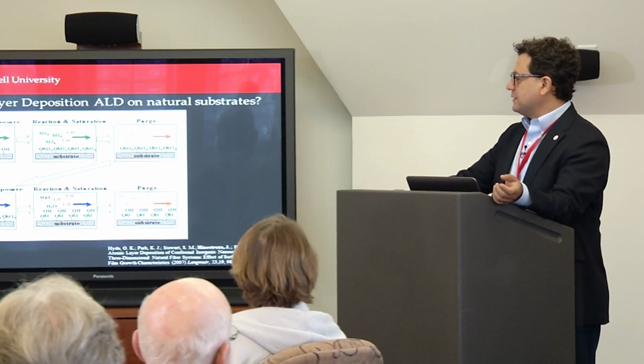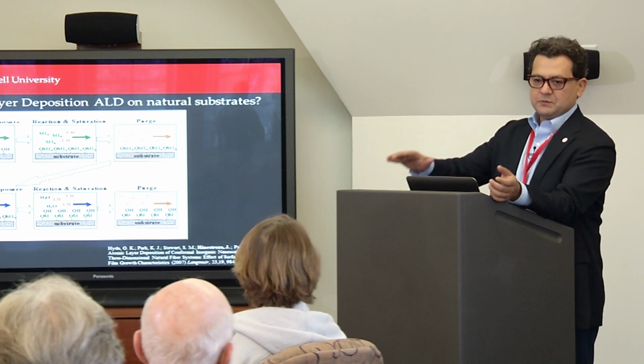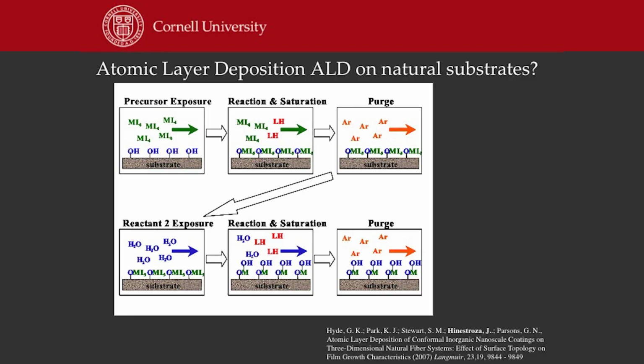Now, what I decided to do is, well, perhaps depositing layers 1 molecule thick, that was fun, but why don't we just deposit layers that are 1 atom thick, much smaller, yeah? So we decided to go smaller. We use a process called atomic layer deposition. It's a very similar process to the previous one. We deposit layer by layer. But we use a very, very expensive chamber. We enter the precursors, there is a reaction, and we create the layers. This is a collaboration with Professor Parsons at NC State. And there was a lot of skepticism because this process can only work on semiconductors and transistors and integrated circuits. But now we try to do it on cotton, yeah?